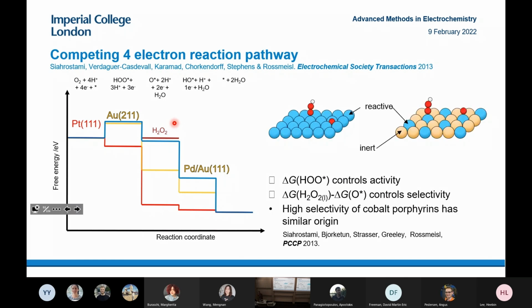And the reason for this is essentially, if you think of a pure metal surface, typically when you're going from OH to oxygen, OH binds to top sites and oxygen binds to hollow sites. However, on a palladium gold surface, oxygen won't bind onto hollow sites because they're coordinated by too much gold. It'll only bind to the palladium and be forced to sit on top, in a position where it's less stable. So when the palladium is surrounded by gold, you're destabilizing the oxygen without destabilizing OOH.